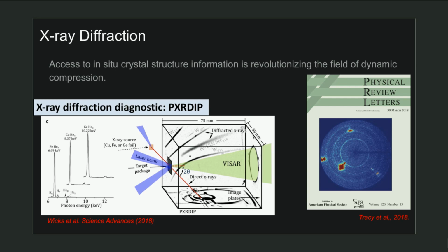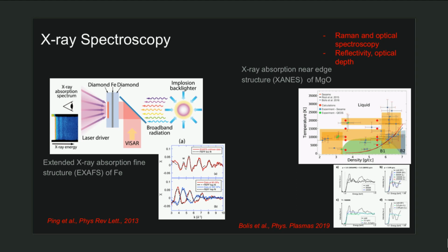But we can also pair dynamic compression experiments with synchrotrons and with X-ray lasers. The example that I show here is an X-ray diffraction pattern collected at the Dynamic Compression Sector at Argonne National Lab, where Sally Tracy measured the formation of stishovite using different starting materials of SiO2. Other work that people do is developing the spectroscopy techniques at different beamlines. And this is made possible either by using an imploding sphere to emit a broadband, or by using synchrotrons as well.